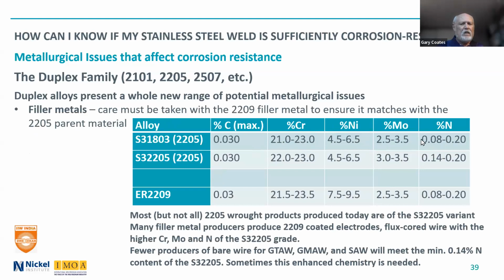that time. But it was quickly realized that if you made the composition to the bottom end of this range, it really was a completely different alloy that had major problems in fabrication than if you had something in the middle range of the chromium, molybdenum, and nitrogen content. So that's where the S32205 comes in. It has higher minimum content, same maximum content, so they really fit into the same